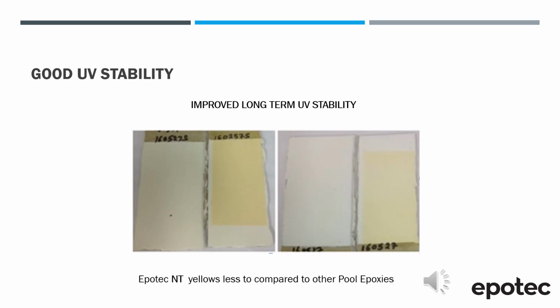If you look at the picture on the left, the old HB used to yellow off quite a bit, and this would mean the paint color would also change significantly over time. On the right you can see EPOTEC NT has a less color change, so we expect our colors will last longer and show a longer service life. This has been proven to be the case since the launch of EPOTEC NT nearly 8 years ago.